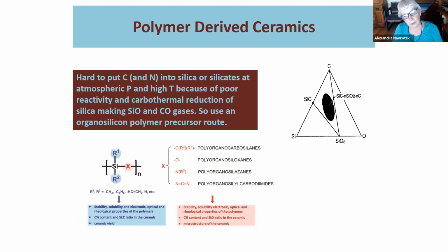But you could not do it directly. You could not do it by simply trying to melt together silica and graphite, because there are high temperature parasitic reactions that make that impossible, plus the materials are very unreactive. So long ago, maybe 50, 60 years ago, chemists started experimenting with silicon backbone organosilicon polymers, with the idea that if you could make a polymer where the backbone was silicon and the pendant groups were various organic groups, and then you would very carefully heat that polymer under anoxic conditions, that is, you would char the polymer, you would get something that perhaps would incorporate the carbon into the silica phase, since the carbon was already distributed on an atomic scale in the polymer.